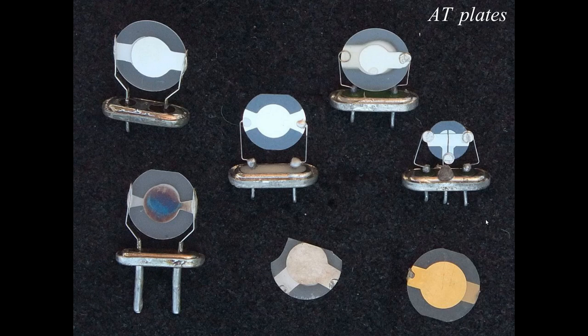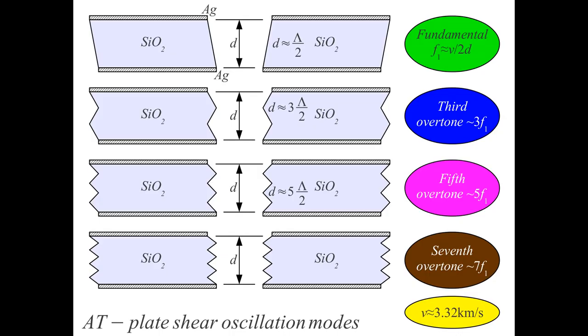So this is how modern-day quartz looks like. This quartz may work in air at 1 bar without degrading the Q of this crystal. The unloaded Q may get above 30,000 with such quartz plates. This is actually a relatively cheap device, a very high performance resonator to build our high performance oscillators.